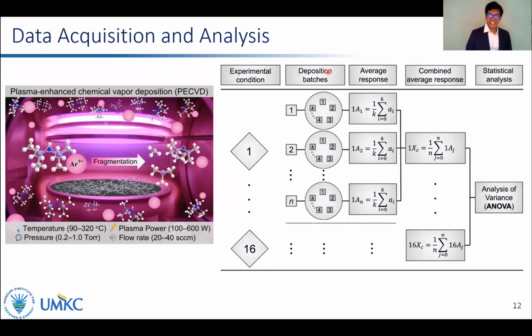Within each deposition, we fabricated multiple thin film samples - you can imagine keeping multiple substrates in the center of the bottom electrode in PECVD. So an average response or property was calculated from all the samples where applicable, such as in the case of spectroscopic ellipsometry.